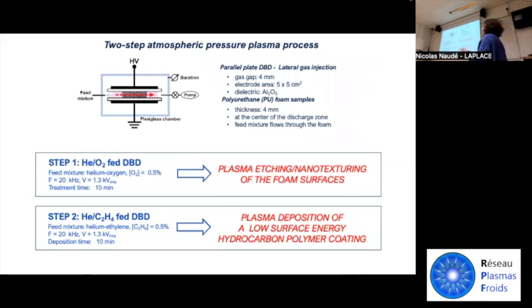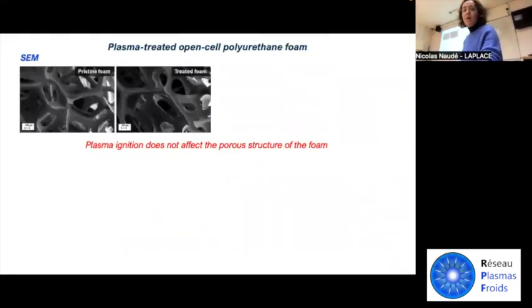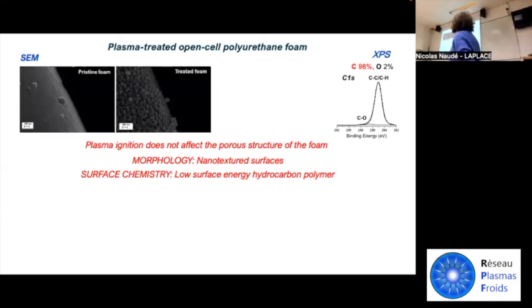That is, in the first step, we used an oxygen-fed DBD to achieve the etching and nanotexturing of the foam surfaces. And then in the second step, we coated the foam with the low surface energy hydrocarbon polymer by using a DBD fed with ethylene. Again, also in this case, from the SEM images, you can appreciate that the two-step plasma process does not alter the porous structure of the foam. However, if we move to high magnification images, it is possible to see that the plasma treated foam presents nanotextured surfaces.